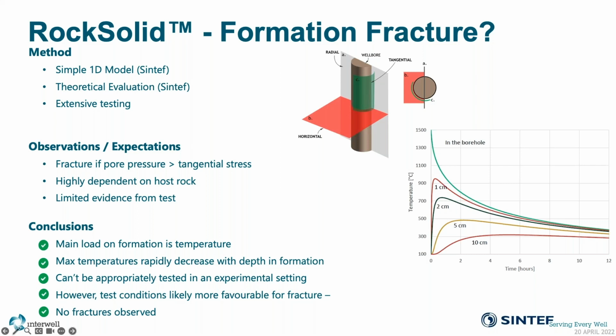However, there were no observed fractures of any kind during any test that was conducted. And the conclusion was that test conditions were likely more favorable to create a fracture system. However, again, none were observed. Of the type of possible fractures, the tangential fracture type was the one most likely to occur, as surrounding stress pushing inward into the borehole has less supporting pressure pushing back, causing those initial first layers of the borehole interface to potentially fall into the hole itself as that hole is created.